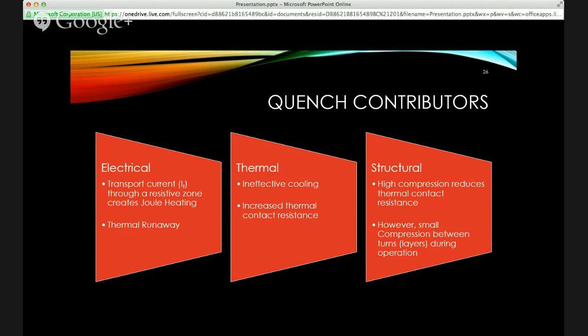That could lead to quenching. You could have an increased thermal contact resistance, meaning when you have those, in order for the superconductor to operate, it's connected to current leads. And if you don't have correct cooling, then you could have some issues there with temperature, with thermal propagation from the current leads actually affecting the superconductor itself. Then on the structural side, the high compression can reduce that thermal contact resistance between the layers themselves and actually ensure better cooling.